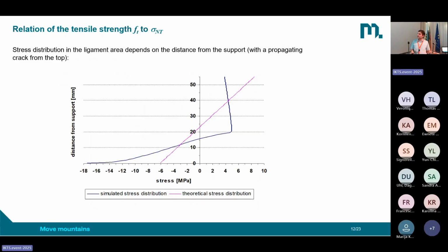How does it look later? So we have now the crack already propagated, you see, to this 20 millimeter mark. That's why the stress in the simulation decreased already. It decreased most at the top where the crack initiated, because here we have already the highest strain and the highest displacement, but it still did not decrease to zero. So there is no completely open crack. And then you see in comparison here the stress distribution from the assumption for the nominal notch tensile strength. So we see there are significant deviations. And if we would say we take the nominal notch tensile strength as a representative for the tensile strength, then we know it's not accurate.